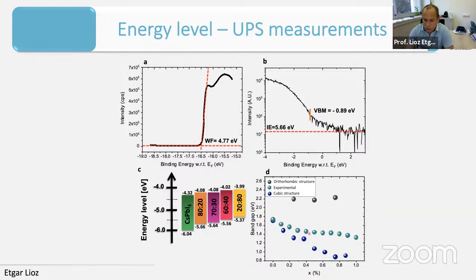What was very interesting to observe when we did some calculations: if the material can create an orthorhombic structure or a cubic structure, this is the blue dots, you can get those kinds of trends in terms of the addition of tin. The experimental data is really standing between those two, which means that we are not exactly orthorhombic on one side and not exactly cubic on the other side. This is because we have two radii, of the lead and the tin, in the structure. This predicts very nicely what we observe when we put more and more tin into the material.